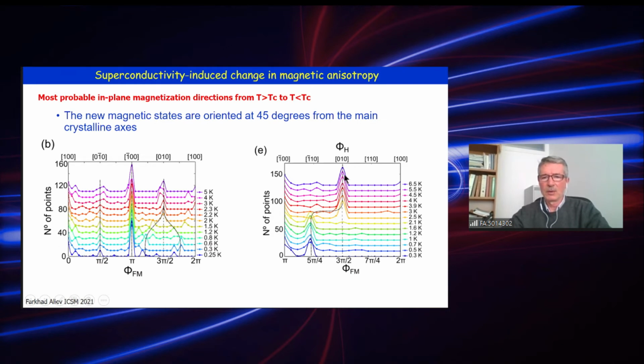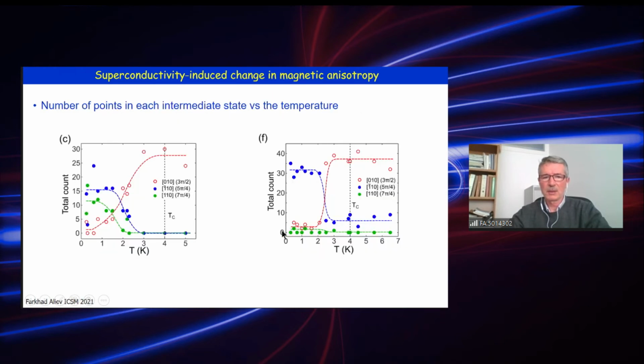We see this more or less clearly, because if we pass to the anti-parallel state, domain walls are probably formed before. But clearly we have a shift from the reference easy axis into a new easy axis, which is oriented at pi/4 with respect to the main axis. This happens in the superconducting state—the amplitude of the probability to find the system in the new orientation increases below critical temperature.